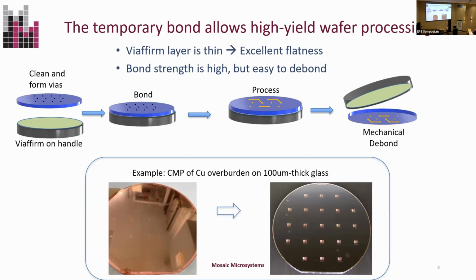And the nice thing about this bond is it's actually strong enough that, for instance, a CMP process, which provides plenty of shear, even grinding processes, which might be even worse than CMP, the bond is unfazed by that. So you can take here, this is a copper, the overburden after we filled vias, and this is the wafer after CMP.